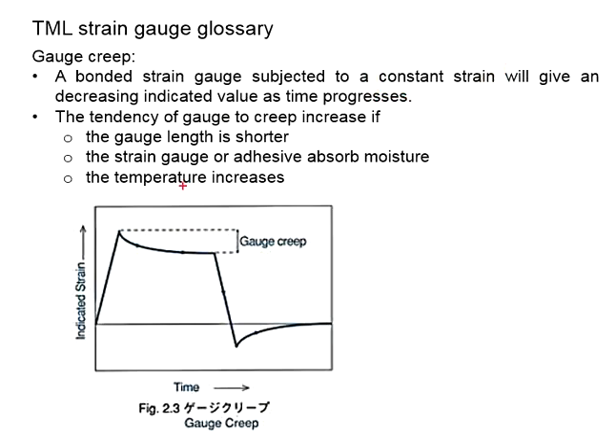In this case, what was indicated by the strain gauge does not fully represent the actual situation of the specimen. This will affect the results. Now, the tendency of the gauge to creep increases if the gauge length is shorter, or if the strain gauge or adhesive absorb moisture, or if the temperature increases. If you need to measure the strain of a specimen which is likely to be held constant over a period of time, probably you can take this into consideration. Use longer gauge length, do proper protection for the moisture, and ensure the temperature is not an issue with the testing.